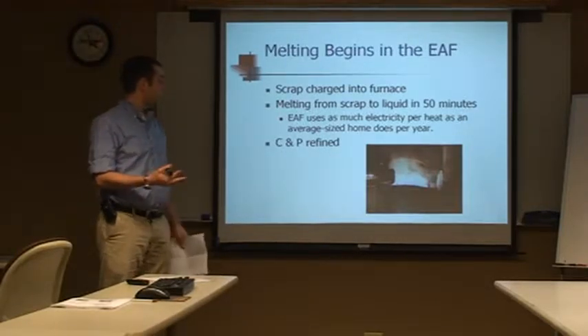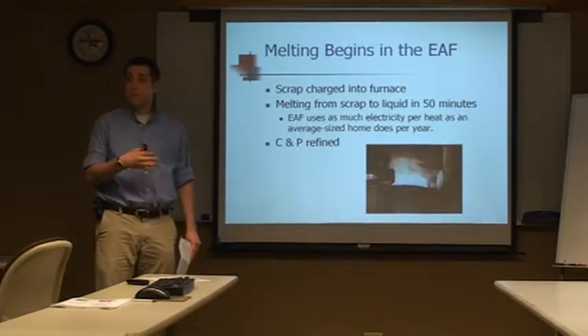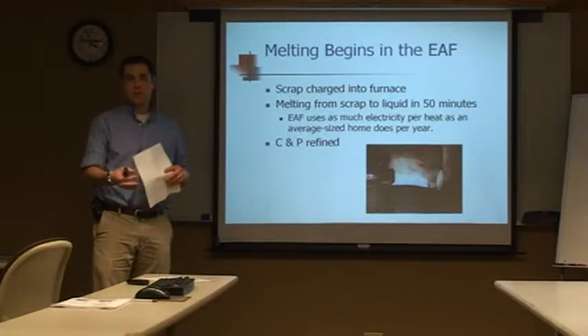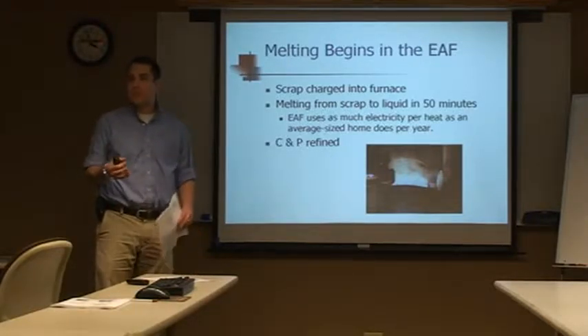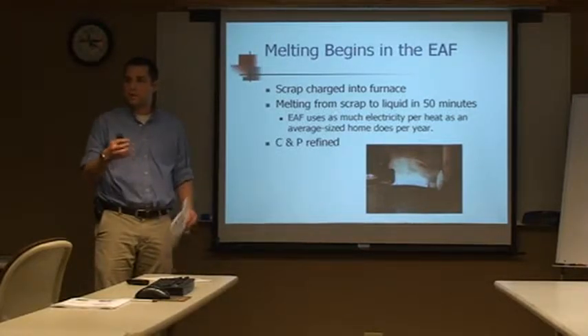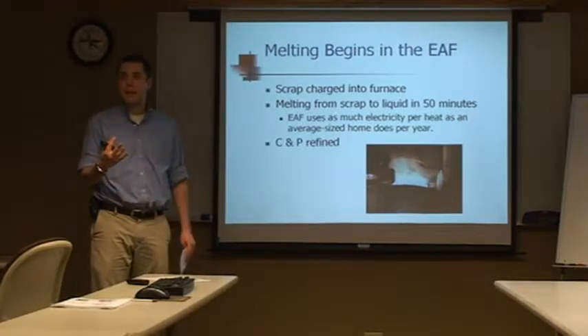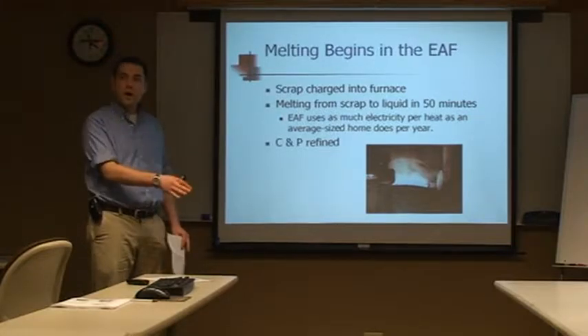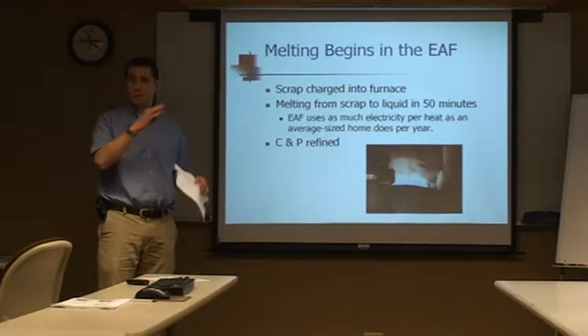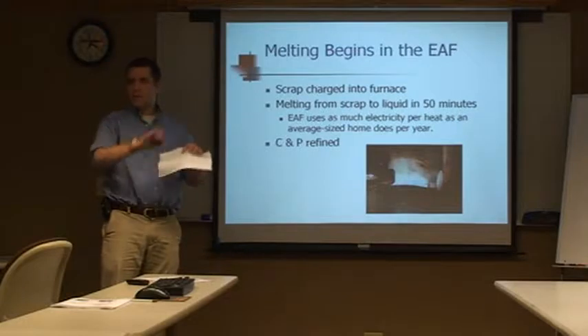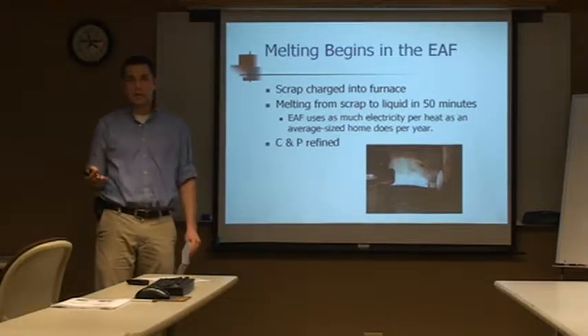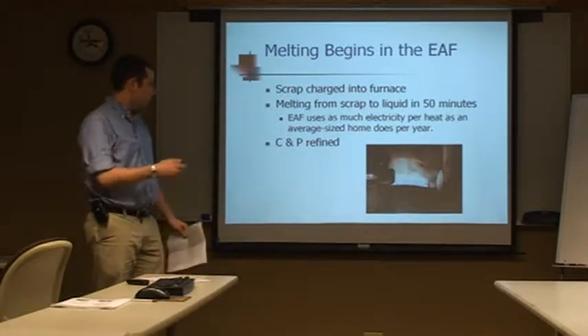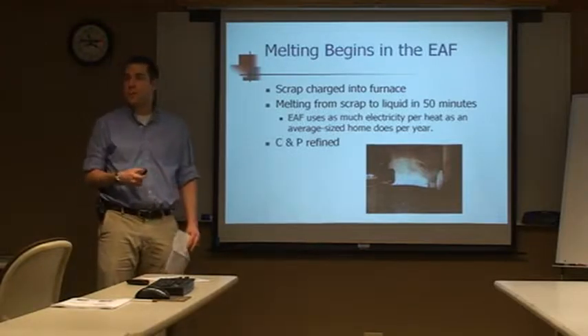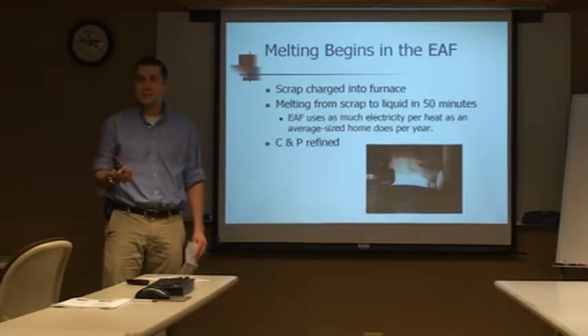We also use the oxygen to refine phosphorus, but instead of making a gas out of it, we make a non-metallic oxide out of phosphorus, which floats up into the slag. And then we drain it off. If you remember in the video, they showed a picture of the slag door, and they had this stuff coming out of the arc furnace. That was slag coming out, and if the arc furnace did its job right, it was slag filled with phosphorus.